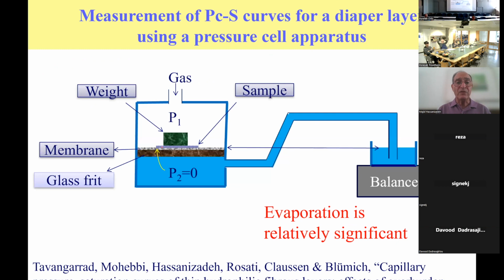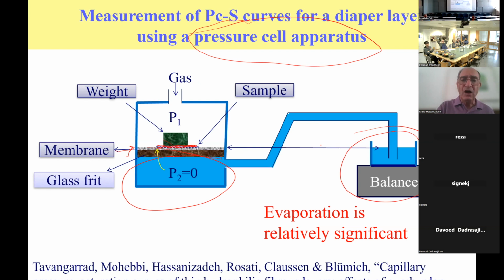This is one of the standard ways of measuring capillary pressure saturation curves for a sheet. The sheet is put here. This is a standard pressure cell apparatus, also used for soils. There is a membrane here that is very hydrophilic and doesn't let the gas go through. Here we have a reservoir of water that always remains full, with no gas going in there. A balance measures the change of weight of water in here, and that corresponds to the weight of water change in the sample.